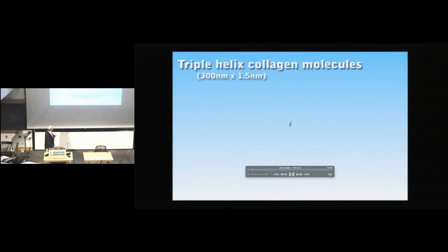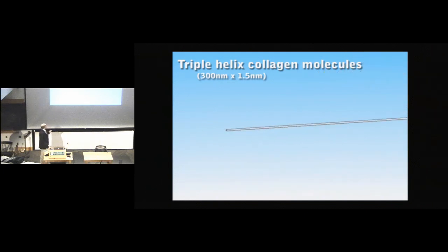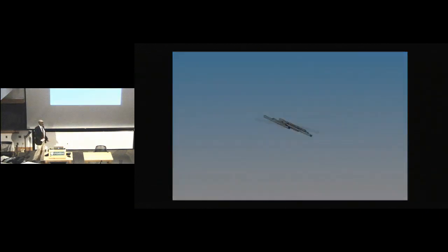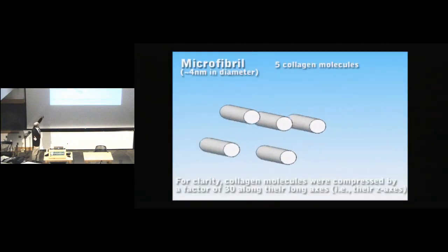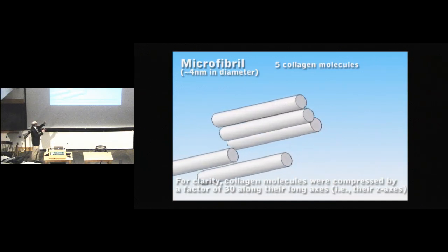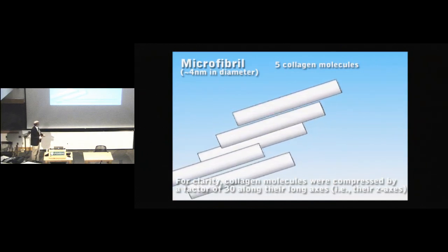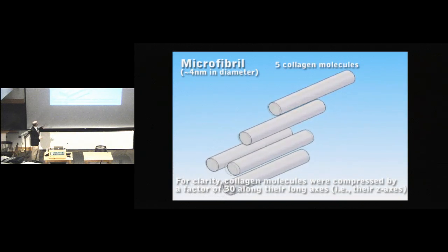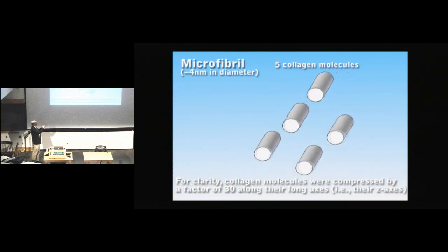All right. So what we start with in our microstructure is we approximate these very long tropocollagen molecules as rods. And then there's a certain stacking that shows up. This is going to be the basis of something like a Bravais lattice. This is how it's all going to stack together. And there's a specific staggering that shows up. This is based on the observations that I showed earlier from Orgel in the chart. And now we crush them down by a factor of 30 so you can see how they come together. So the staggering is a little bit clearer when we shrink down the axis by a factor of 30.